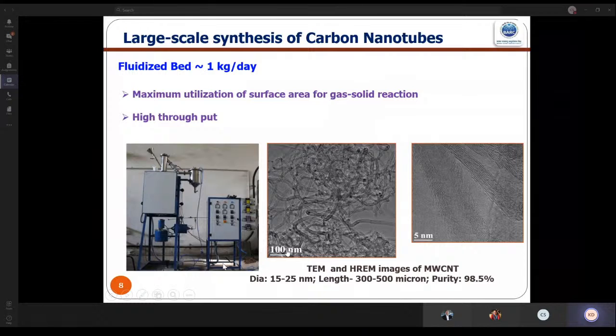In this furnace we can make almost a kg per day, with a diameter of 15 to 25 nanometers, length in microns, and a purity of 98.5%.